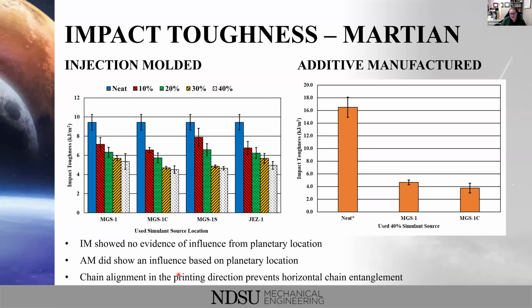And then again, we think it's just the alignment of this chain, which is kind of preventing horizontal chain entanglement. And so our polymer chains are reacting a little bit differently to that, absorbing that energy, which is why, again, our neat polymer went from roughly 9.4 kilojoules per square meter for impact toughness to over 16, which was just really surprising. So we do want to look more into that in the future as we go forward.